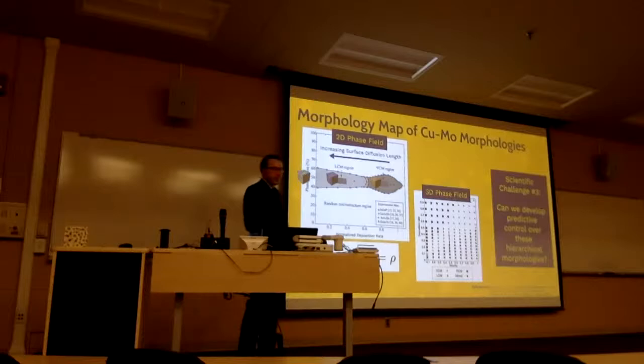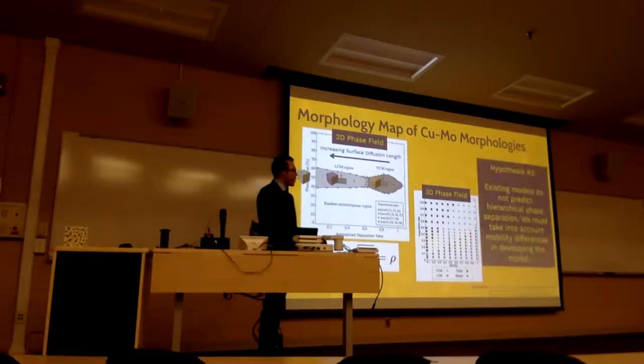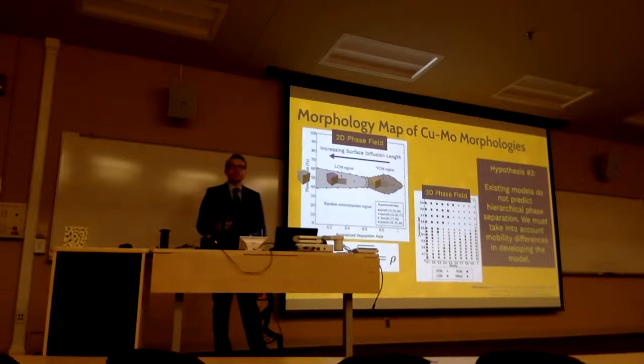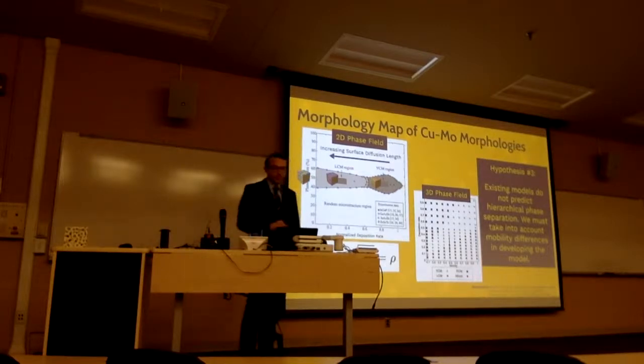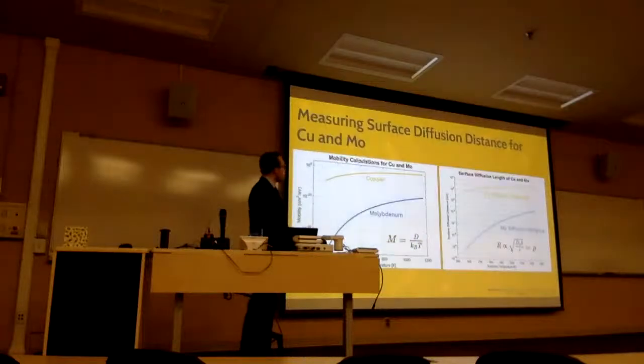But we hypothesize that we actually can't consider just the interdiffusion length. We have to consider the diffusion length for both of the constituent species. What do I mean by that? We need to consider the mobility difference between the two adatoms, or two constituents, to describe this morphology.